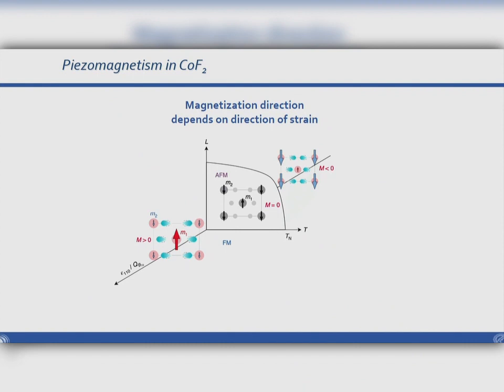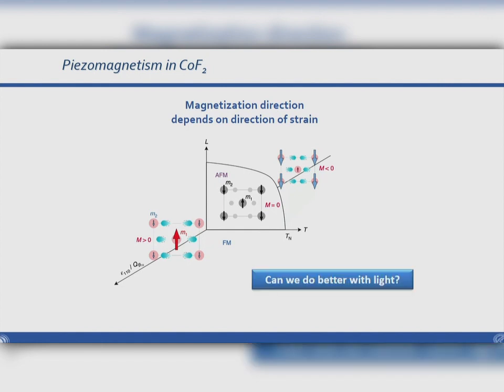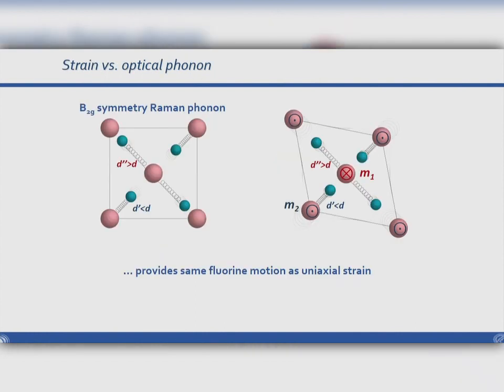And interestingly, in contrast to magnetostriction, this is really linear in the strain that you apply. So if you apply a strain along one direction or the other, this will at the same time change the direction along which you induce this net magnetization. But the question is, can we do this with light, and maybe can we do it even better?